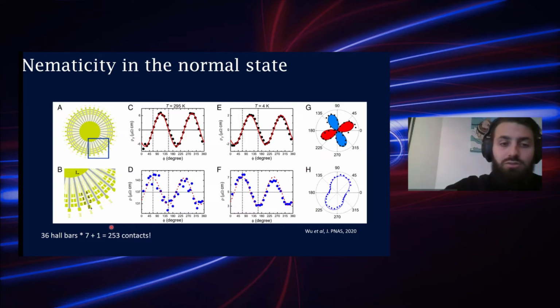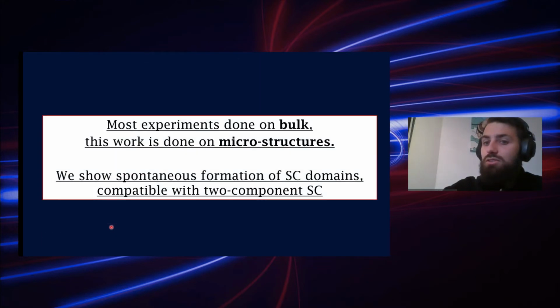So before I continue to our results, I will first highlight that most of these experiments are done on bulk. And if we are actually wanting to research these domains between different components of the order parameter, and the domain wall separating them, it is very important that we also look at microstructures. Since in microstructures we are able to possibly trap a single domain or possibly trap a single domain wall. And that is exactly what we did.